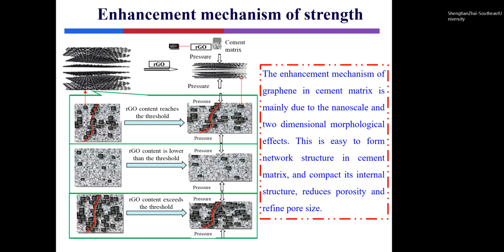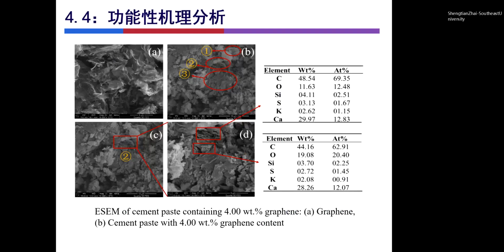This picture shows the distribution of the graphene and the improvement mechanism in the cement matrix. The enhancement mechanism of the graphene in cement matrix is mainly due to the nanoscale and two-dimensional morphological factors. This is easy to form a network structure in cement matrix, and compact its internal structure, reduce the porosity and refine pore size. This picture shows ESEM of the graphene cement-based materials.